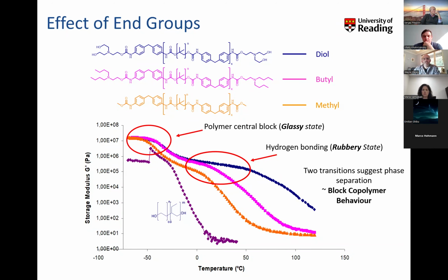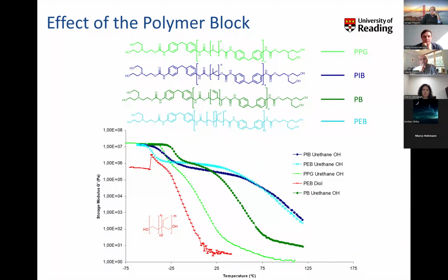Varying the polymer block really did dramatically affect the rheological characteristics. If you have a relatively polar polymer block, such as PPG shown in light green, that second rubbery transition is really very shallow, and the material goes into liquid flow very, very quickly. Whereas if you have apolar mid-blocks, such as polyethylene-co-butylene shown in cyan, or the polyisobutylene shown in dark blue, you can see how that rubbery transition is extended beyond 50 degrees C and relatively level before it starts to enter the viscous domain above 75 degrees. So to have a stronger phase separated material, you really need to have a more apolar mid-block.